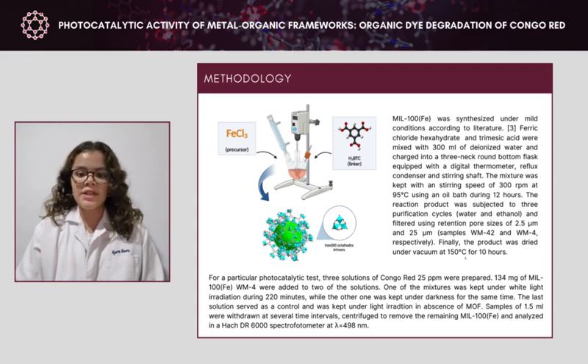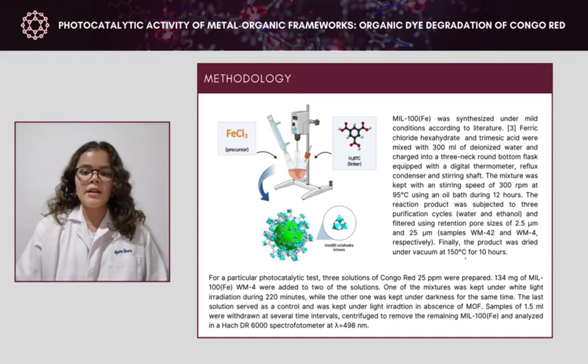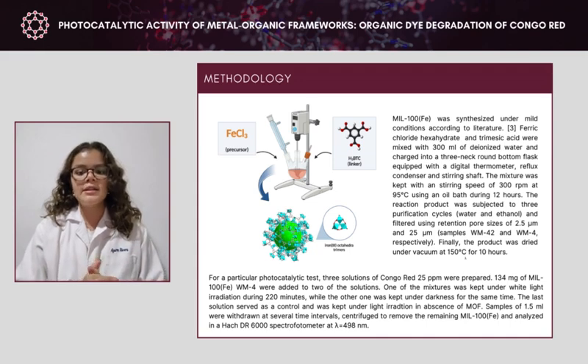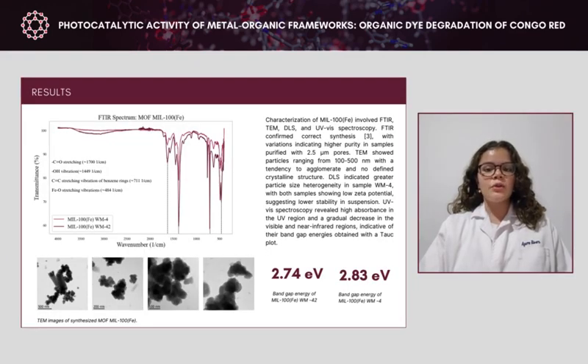For the photocatalytic test, 3 solutions of 200 milliliters of Congo Red at 25 parts per million were prepared. 134 milligrams of catalyst were added to 2 of the solutions. One of the mixtures was kept under white light irradiation for 220 minutes, while the other was kept in darkness at the same time. The last solution served as a control and was kept under light irradiation in absence of MOF. Samples of 1.5 milliliters were withdrawn at several time intervals, centrifuged to remove any remaining MOF, and analyzed in a spectrophotometer at 498 nanometers. Our characterization techniques include Fourier transformed infrared spectroscopy, transmission electron microscopy, dynamic light scattering, and UV absorption spectroscopy.